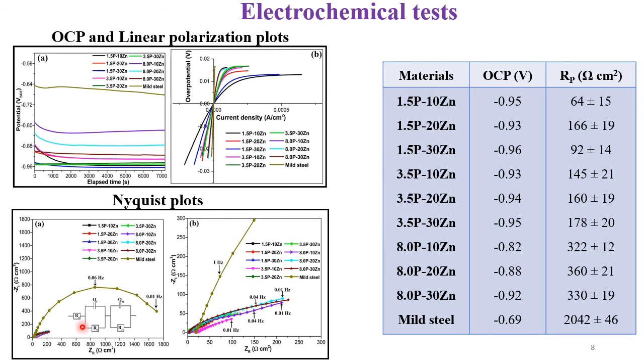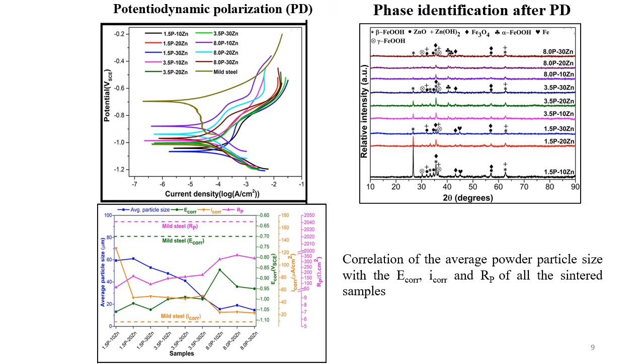Coming to the Nyquist plot, it could be observed that the polarization resistance, or the charge transfer resistance, of all the hybrid samples is much lower as compared to the mild steel. The potentiodynamic polarization plot for all the hybrid samples has been found to be much lower as compared to the mild steel. Along with that, they have shown metastable passivation behavior, which is due to the alternate dissolution of iron and zinc, and the phase identification after PD shows formation of both iron and zinc corrosion products on the surface of the hybrid samples.